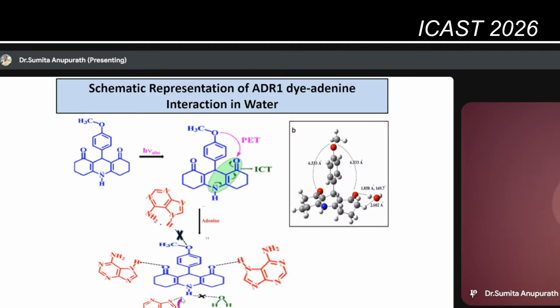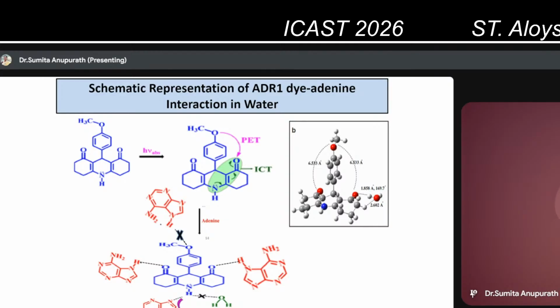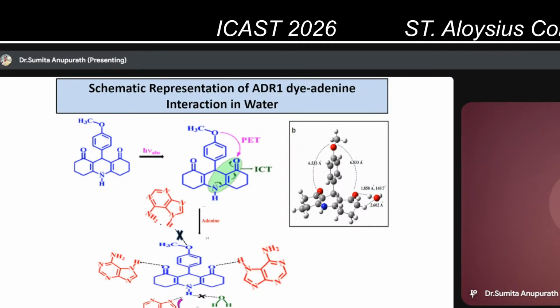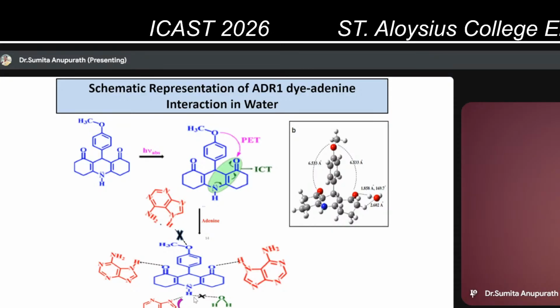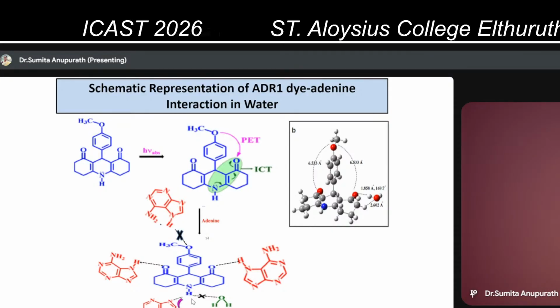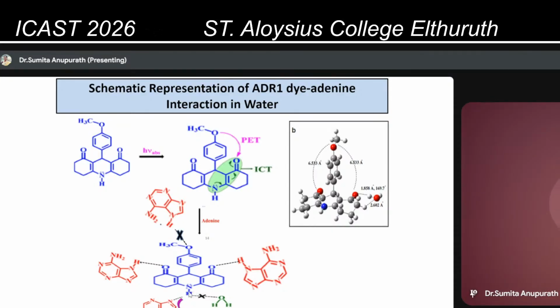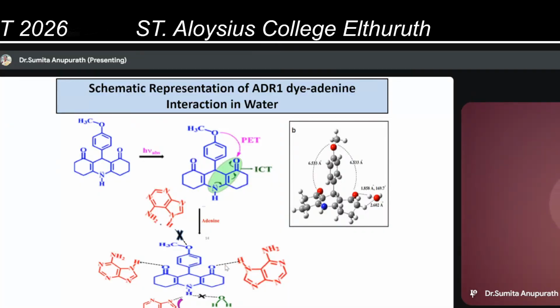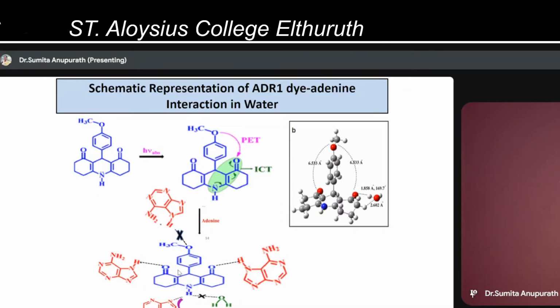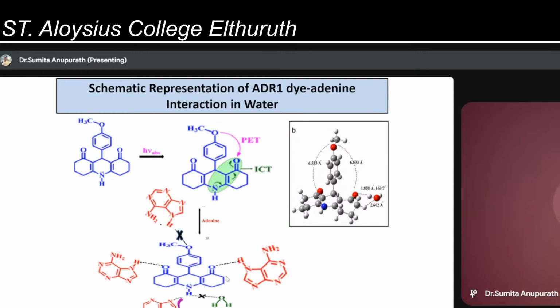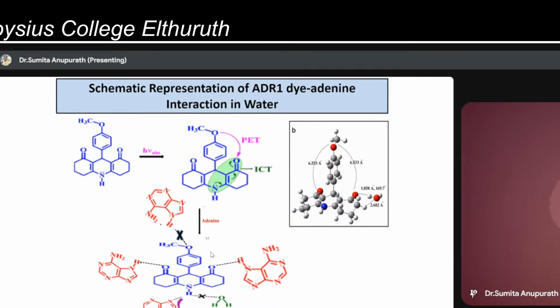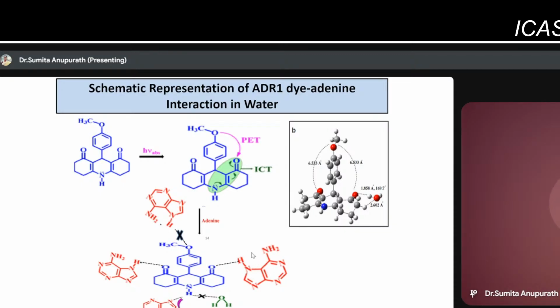Now, this bathochromic shift, or the red shift, which was observed in the emission study is due to the hydrogen bonding at the NH hydrogen, and the adenine molecule, which is also bonded at the carbonyl group of the dye, is not in a position to suppress the PET process because of the geometrical constraints, because for a PET process to be completely suppressed, the guest molecule, here in our case adenine,